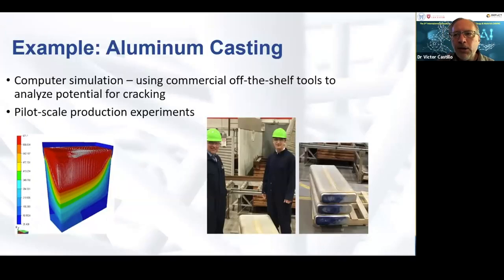another example is from the aluminum industry. So I thank Professor Lieta for showing about aluminum. This is a casting of a much larger bar ingot. These ingots in production are about 5 foot across, about 60 inches. What you see in the lower right-hand corner are pilot plant scale ingots that are made for experimentation. And then you see myself and my collaborator from Oak Ridge National Lab visiting the plant. And we ran simulations,